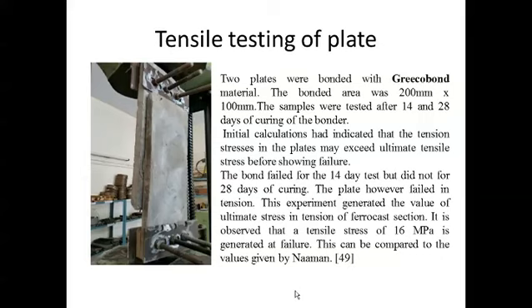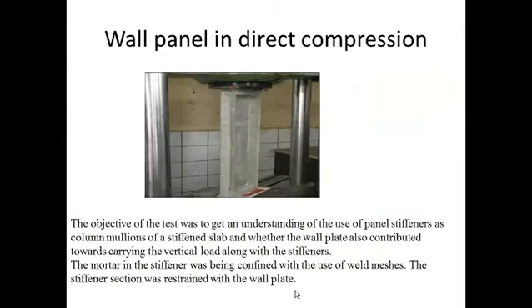We found that after 28 days of curing, we got a tensile strength of 16 MPa. There was no failure at the joints or at the crossheads—it was complete tension failure, ensured by this test setup. This conformed to the tests done by Naaman, and we got similar results when the plate was tested directly.